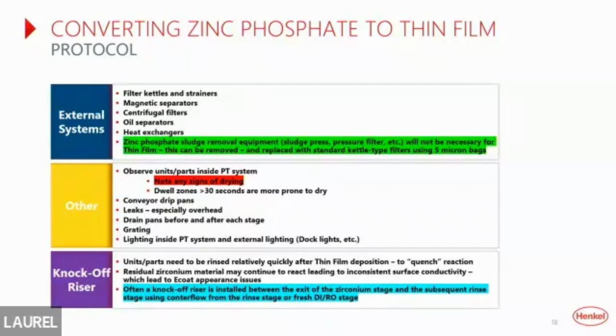When you're walking through the system and looking as production is running, if you can open those doors, you want to look for any drying. Drying is a big no-no. First of all, it's a big no-no with zinc phosphate, but it's even more important with zirconium. Zirconium doesn't give us quite the latitude that zinc phosphate does. So any drying is going to be an issue in the system. So that's an important fact.